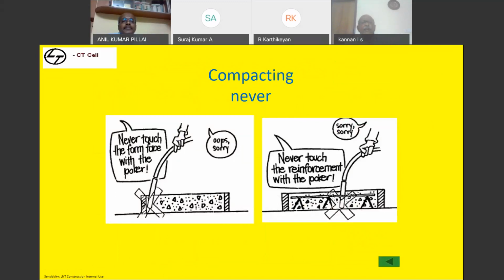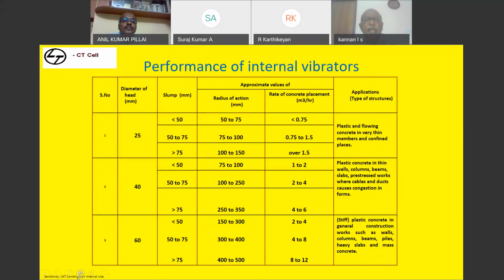So never touch the form face with the poker. And one more thing before that I want to say: suppose you are using a 40 mm needle, you can compact only 4 to 6 cubic meter concrete per hour. In case you are using 75 mm slump concrete with a 60 mm needle, you can compact only 8 to 12 cubic meter concrete. So this is what is possible with a single needle.